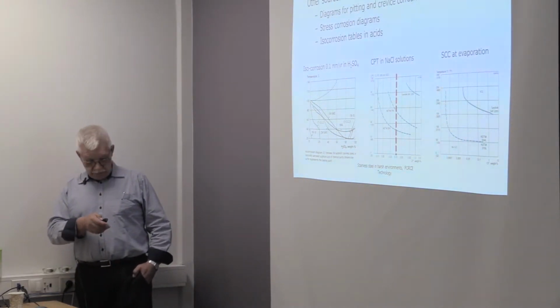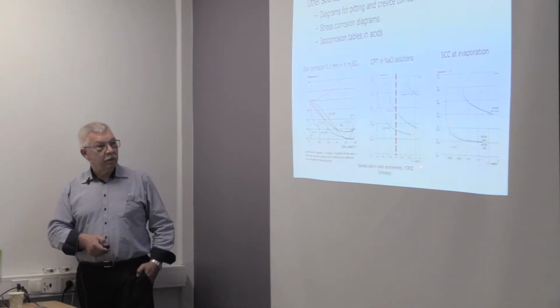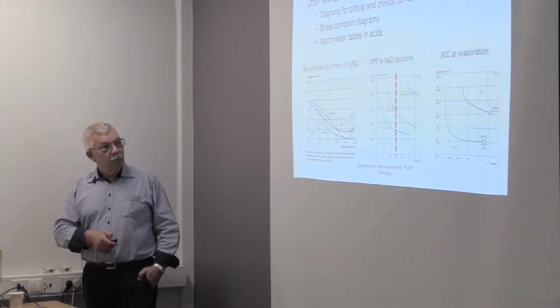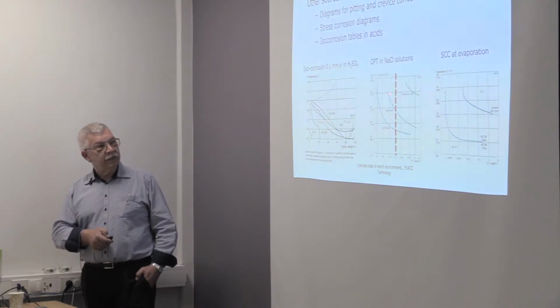And as you can see, if we choose a certain chloride level, 0.1 percentage of chloride, then we can see that a 304 stainless steel will not be able to go above some 30 degrees C before we have pitting corrosion. 316, then we are at 55 or something like that. And if our temperature is higher, we need to have a higher alloy, for example, this duplex stainless steel.